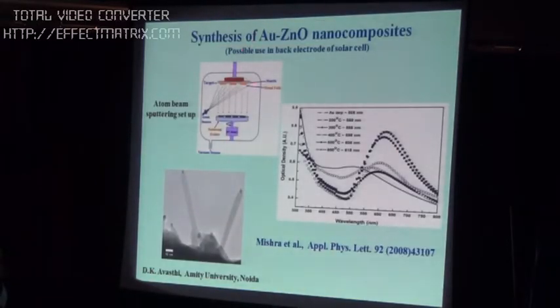Here again is the ion gun used. You have metal pieces here, and then a zinc oxide matrix here, and you shoot atoms with a source. Then you get sputtering of atoms and molecules from gold and zinc oxide, and by a self-assembly process, the metal embedded in zinc oxide is formed. This is possible in thermal evaporation also, if you do simultaneous evaporation from two sources.